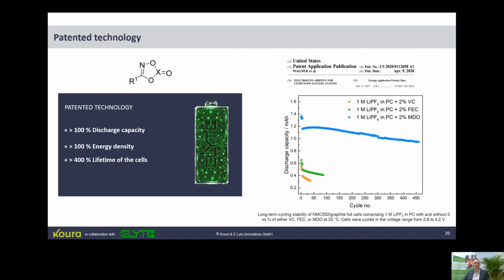So on the right-hand side, you see in principle the proof of concept. And I want to highlight this. This is actually really a proof of concept because we use an electrolyte formulation which does not work without any SEI additive. Okay, PC is well known to lead to ongoing graphite exfoliation. Yeah, and by using different SEI additives, we can basically compare our new technology to the standard technology.